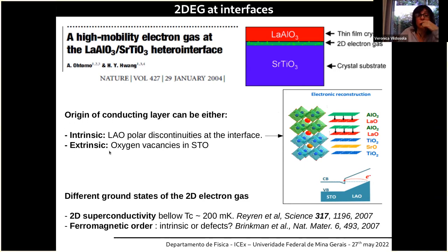But there are some other, extrinsic ones: the oxygen vacancies in the strontium titanate, which also can be controllable in certain experiments, and the charge left behind by the oxygen gets trapped at the interface, also contributing to these 2D metallic states. These 2D metallic states can have different ground states. It was observed that they can develop a superconducting two-dimensional phase below a very low temperature, 200 millikelvin. They also observe, for instance, ferromagnetic order. There is some debate whether this ferromagnetic order is intrinsic or due to defects, but the physics that leads to the states at the interface of these oxides is really rich and very interesting.